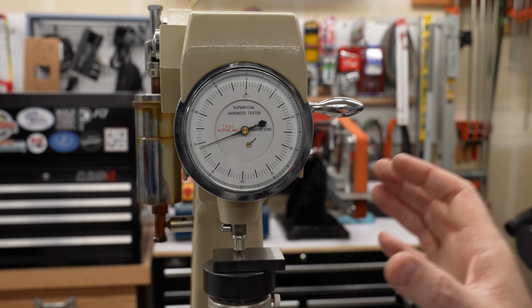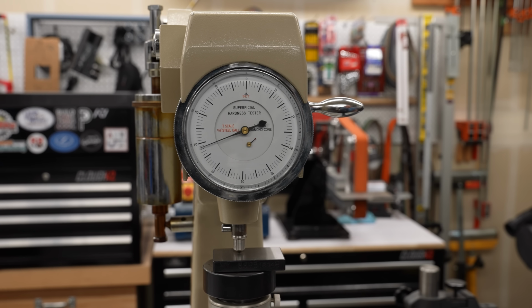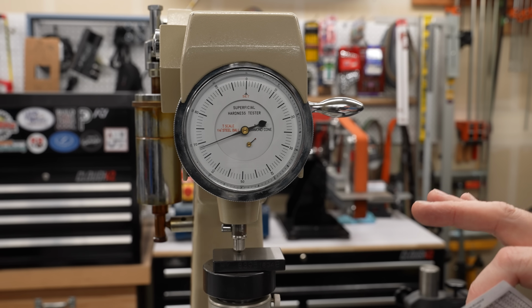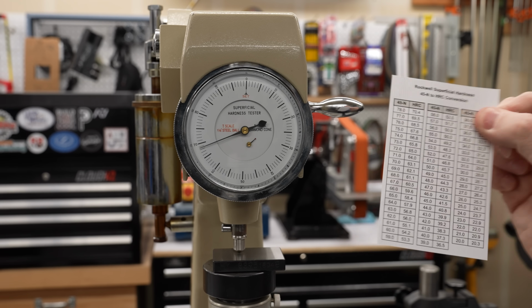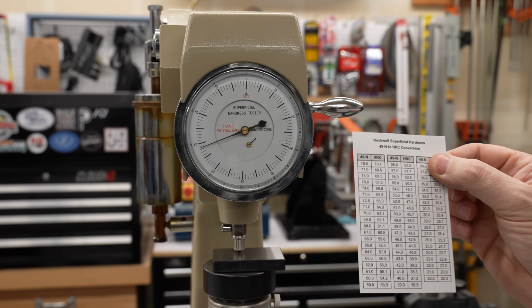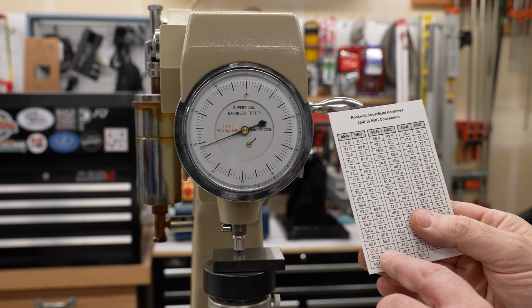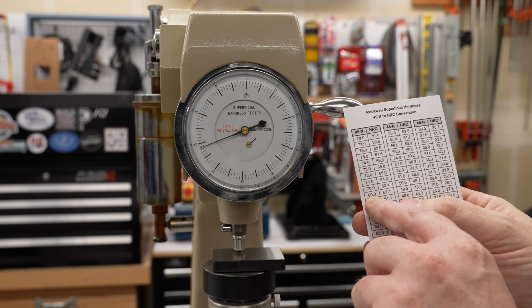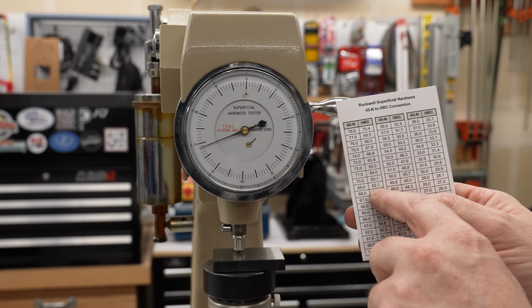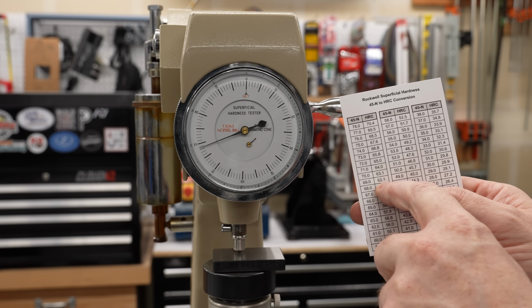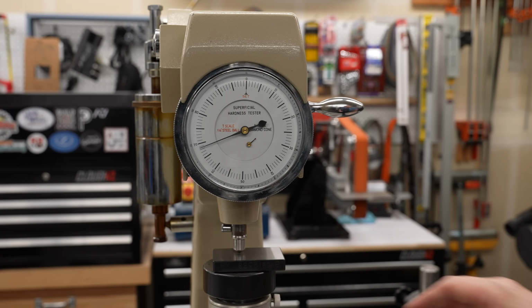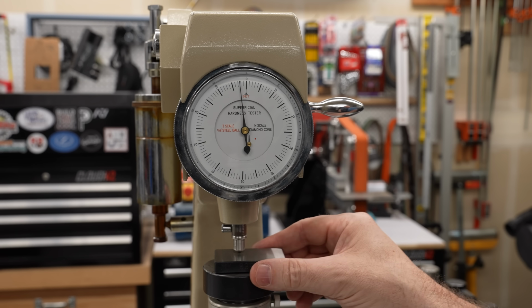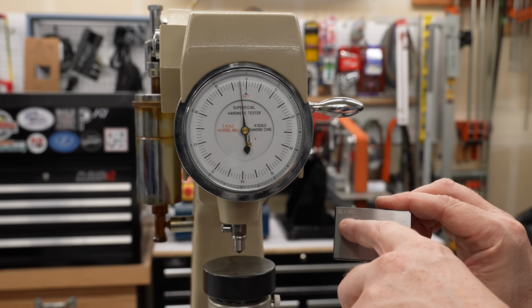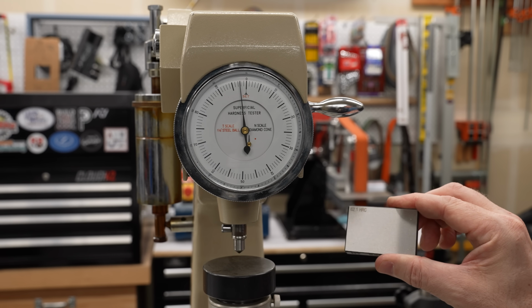I would actually like to know the Rockwell C hardness of this part, because that's what I care about, and if I had found a Rockwell C tester at a swap meet, I would have bought it. But I have a conversion chart that I put together here from sources available on the internet, and we'll just come down here and find 69 45N, and that is equivalent to 62.1 HRC. And lo and behold, 62.1 is exactly what is laser marked on the side of my test standard.